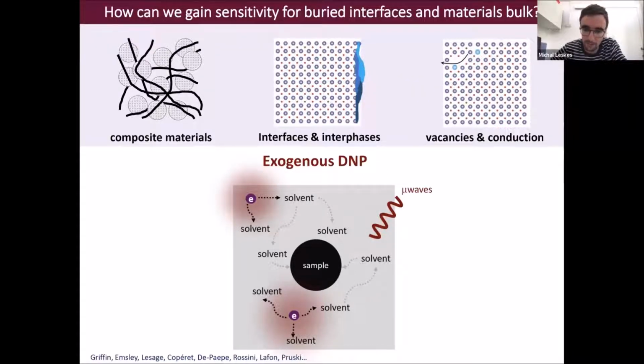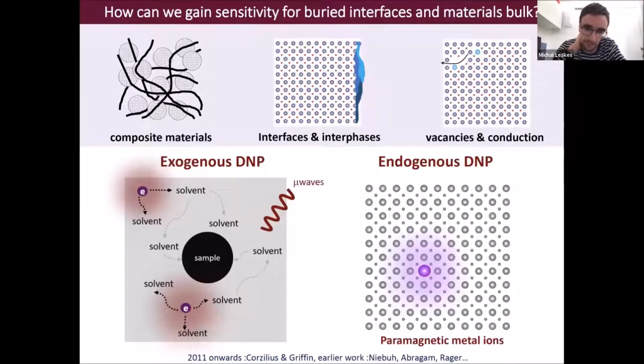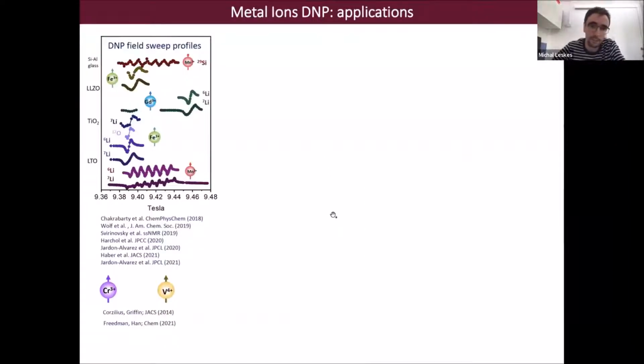So instead of that, our group has been focusing on a fundamentally different approach, which consists in introducing the source of polarization directly into the bulk of the samples. We do this by doping our inorganic crystals with paramagnetic metal ions, which then, upon microwave irradiation, can transfer the polarization to nearby nuclei. Over the last few years, our group has made a lot of effort to demonstrate the feasibility and the versatility of this approach by doping a series of different samples with various paramagnetic metal ions. Most prominent are iron 3+, gadolinium 3+, and manganese 2+.